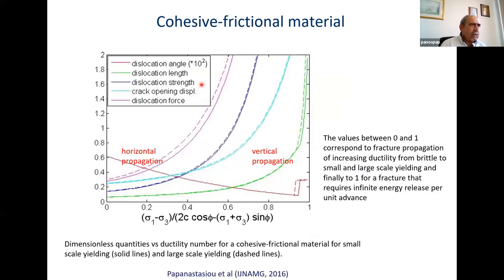Similar results for the case of the cohesive frictional material. Now the critical parameter is a combination of the stress field as before and the rock strength. Now we have the cohesion, we have also the friction, but this is the critical parameter. Again, when the front propagates horizontally, it's here, easy to propagate and induce the fracture. And when we move to here, for propagation in the vertical direction, you see more energy is needed, increasing dramatically, to induce and propagate a fracture.